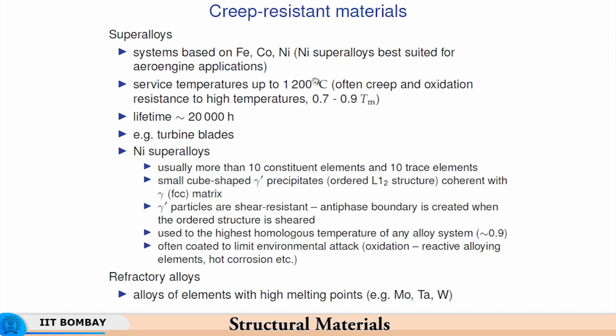So, these are some of the issues which have to be kept in mind when one chooses material for high temperature service. Not only the creep, not only resistance to the mechanisms of creep, but one has to resist oxidation also at high temperatures. So, lifetime has to be close to about 20,000 hours of actual operation. It is not 20,000 hours from the time you have installed the superalloy part in the equipment. These are 20,000 in service hours.